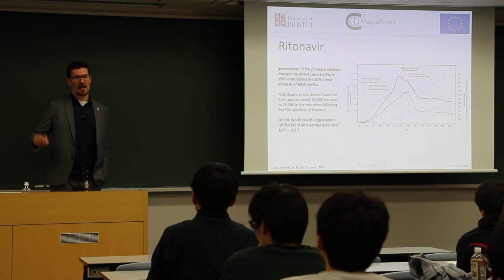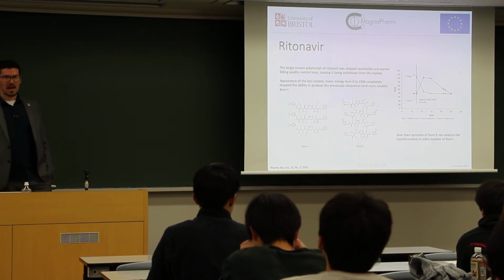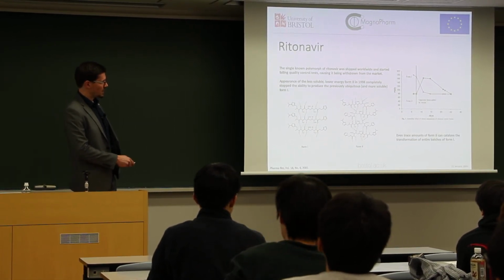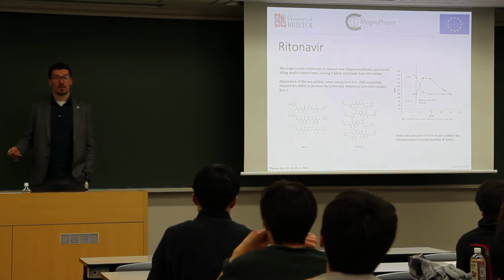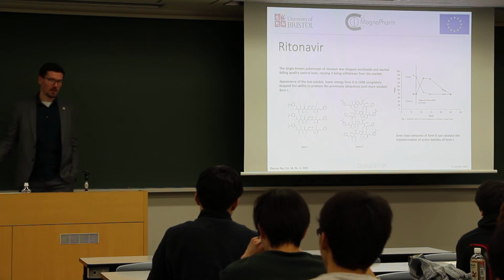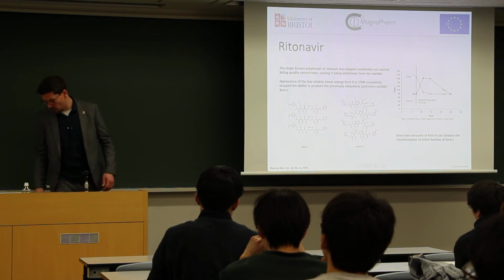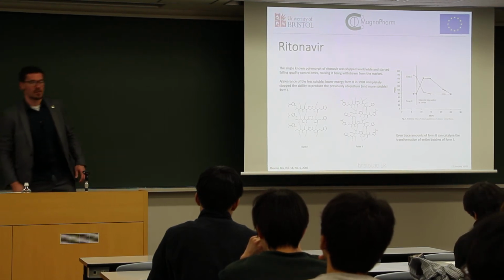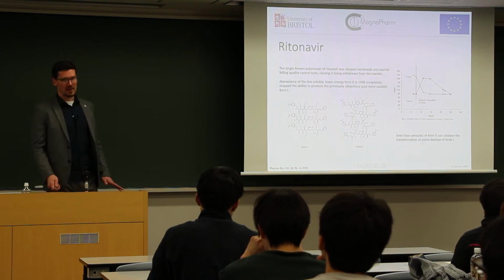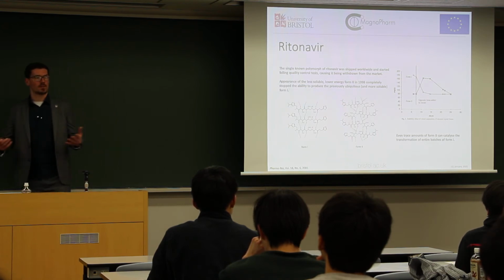People were taking it, and it just wasn't doing what they needed it to do. What had actually happened was there was a second form of ritonavir, a second polymorph, form 2, that they hadn't found. So all of these pills that they distributed around the world were form 1. People were taking it, it was dissolving, going into the blood and doing its job. The molecule was fine. However, form 2 appeared, and all of a sudden, it wouldn't dissolve.